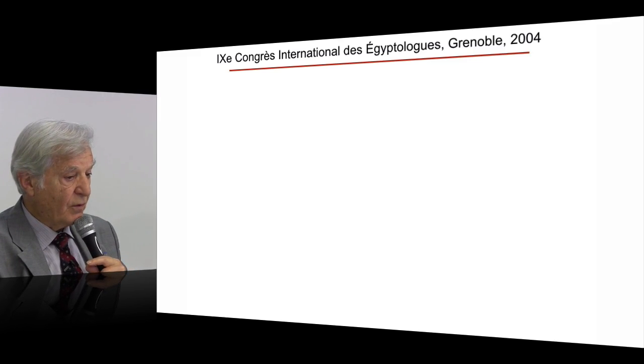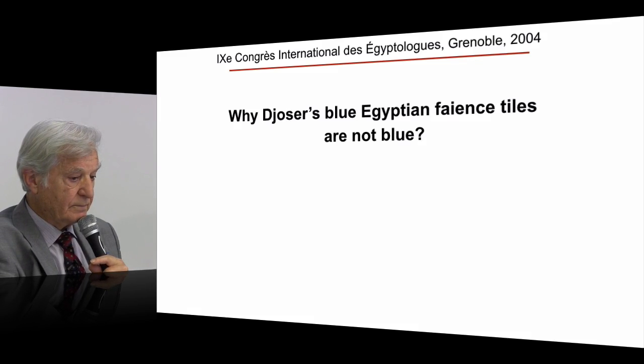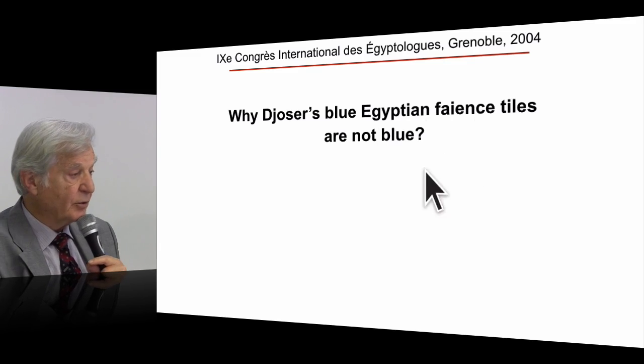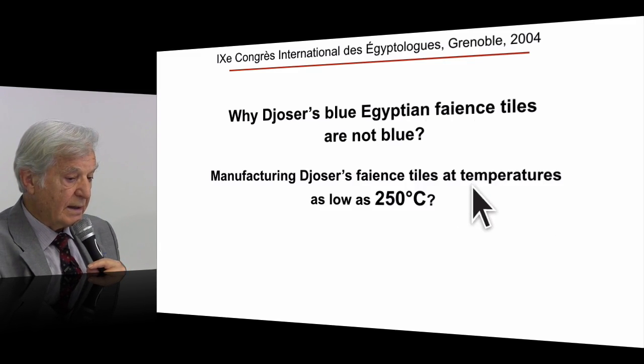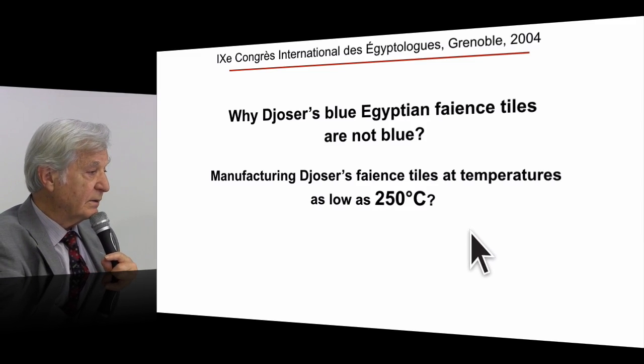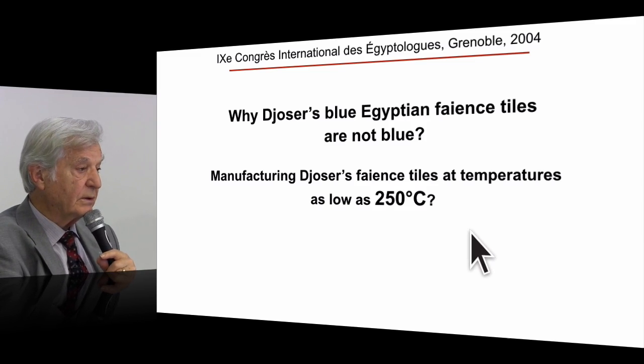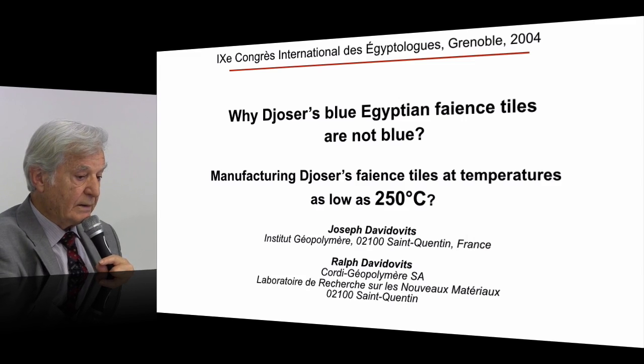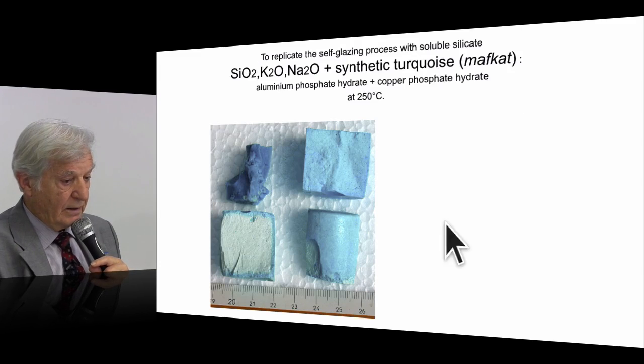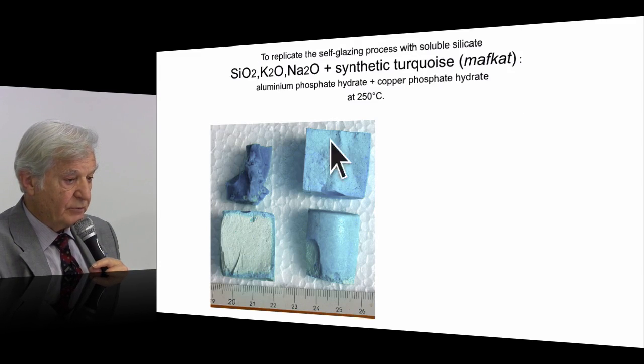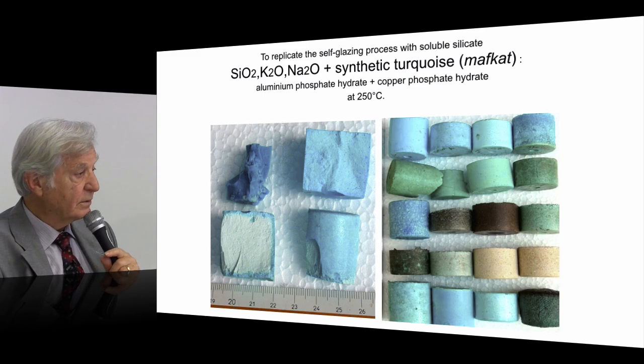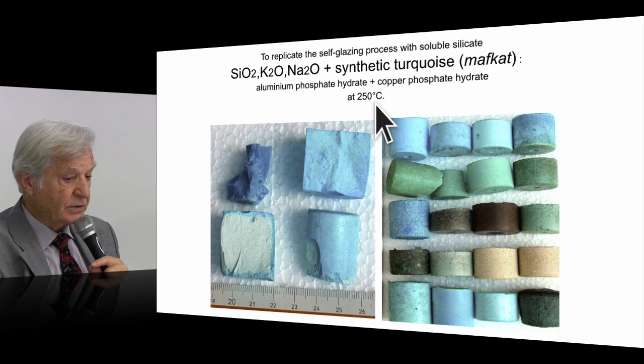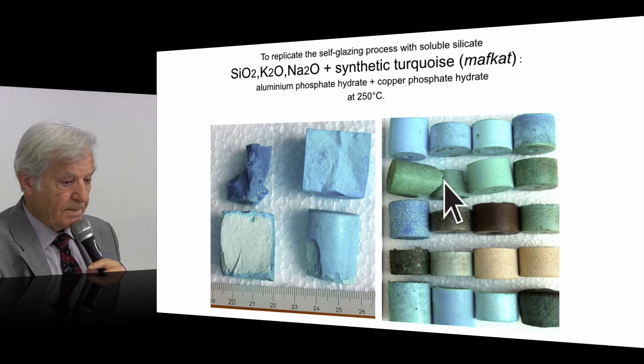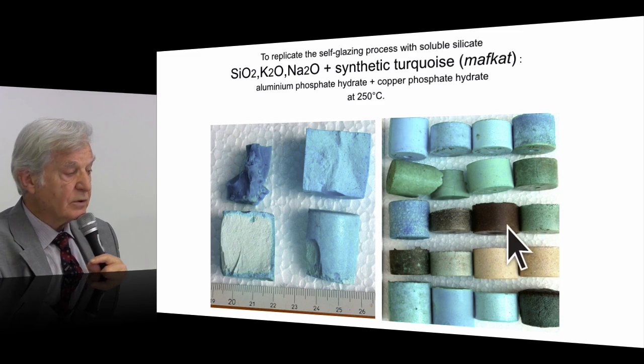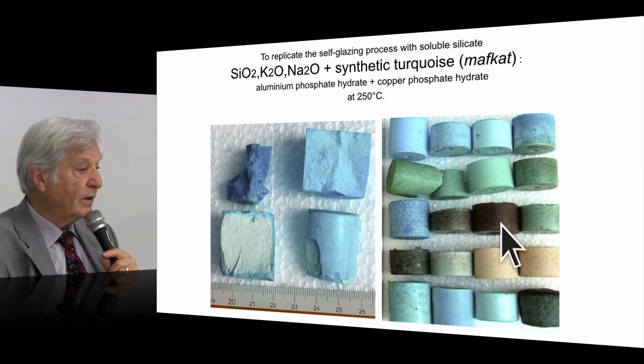So we presented in 2004 our first result on the subject: why Djoser's blue Egyptian faience tiles are not blue. Manufacturing Djoser's faience at temperatures as low as 250 degrees C. The geopolymer technology allows to do it at low temperature. And we made a replica of this coloration with a synthetic turquoise, and we got samples at 250 degrees C that were blue for potassium, green for sodium silicates, or black if the samples were heated above 300 degrees C.